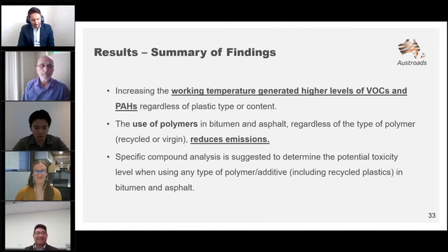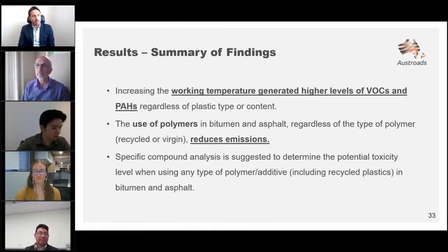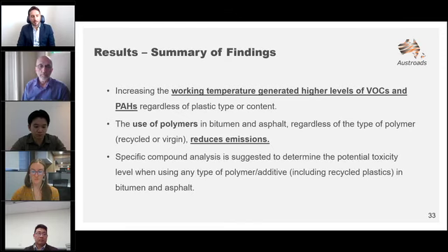So we got the method from a report that was published last year in the United States, which is the summation of probably 4 or 5 years of experimentation on this. We have adapted it to the Australian conditions. Obviously, we wanted to validate it against the available RAP in Australia. That's specifically for the crushing and the similarities between the gradation from a real field RAP and the gradation we got after that Los Angeles crushing process, part of the process. It would have been much easier to just age the loose asphalt mix and put it back into the asphalt, but that's not really similar to what's happening in the field, where you need to take it out of the road first, bring it back to the plant, crush it, and then reuse it.